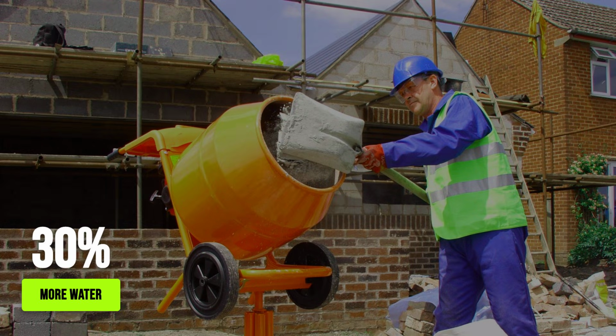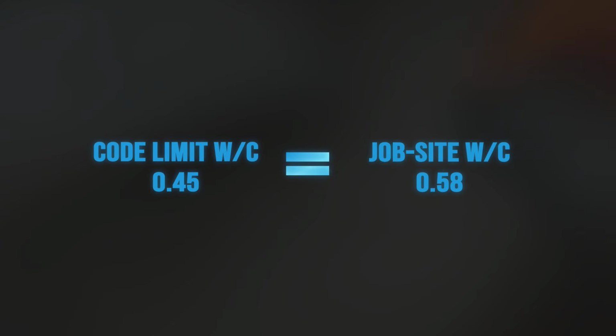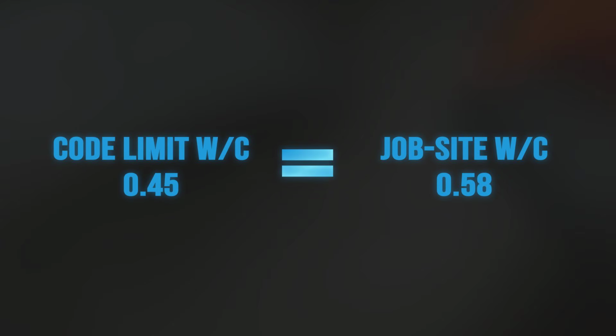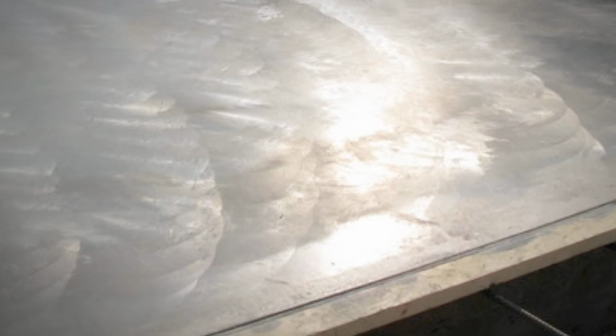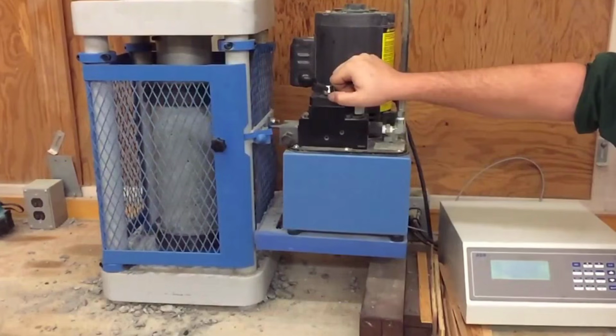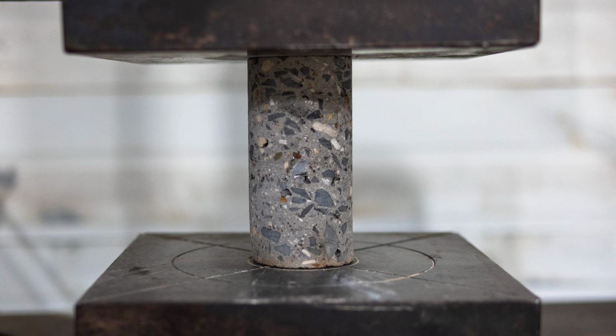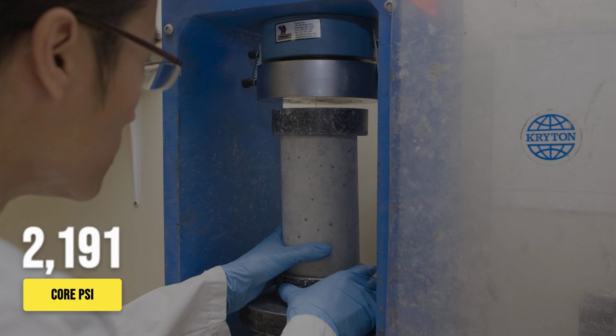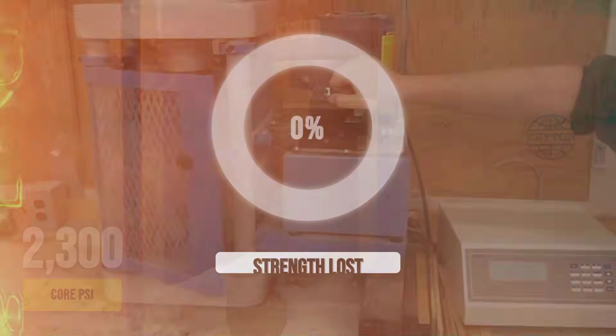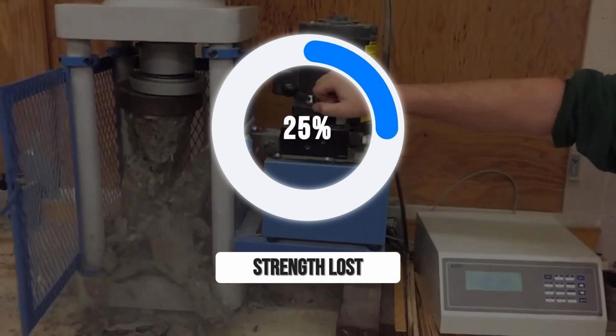In practice, a foreman will add 30% more water to a batch to keep the pour moving. The result is a water-cement ratio that jumps from 0.45 to 0.58. The impact is invisible to the naked eye, but devastating in the lab. A 3,000 psi design now yields a core strength of 2,200 to 2,400 psi, up to a 25% loss in